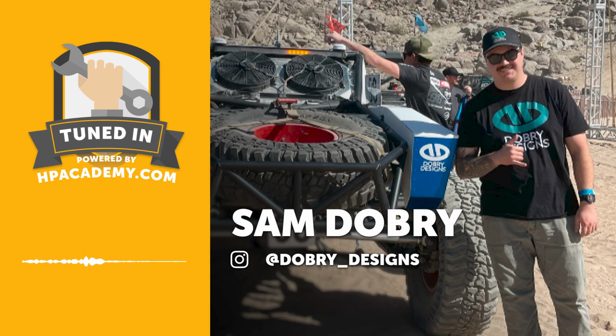Okay, so a couple of things I want to dive into here. First of all, just talking about the heat input into the weld area, this really defines the welding process that is viable for use with 4130 chromoly, in so much as it is solely TIG welding that you'll use with chromoly construction, as opposed to MIG where we don't have the heat control, correct? So with TIG, your heat is a lot more linearly controlled with your penetration, so you are kind of set to one mechanism there. But with MIG, you're tossing in a ton of extra material, so you're often building up that weld joint a lot more, and making it a lot stronger just because you're adding that much excessive material into your system compared to TIG welding.